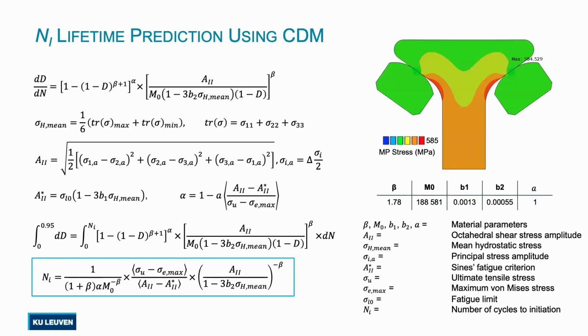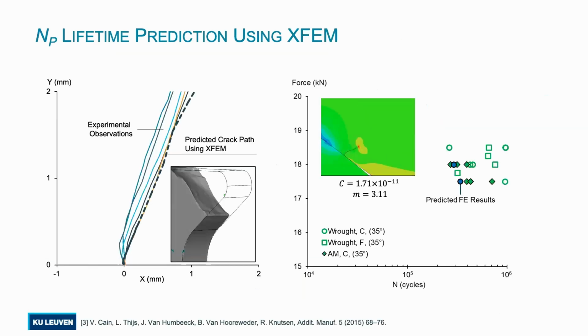We did also some simulations to confirm that. Two more slides, and we used continuum damage mechanics. The main reason for this simulation is to understand the behavior and integrate the defects inside the finite element model for crack initiation. And also we try to estimate the crack propagation path using an extended finite element model, and adding all together, you see that we can predict the results well compared to the AM material. And the next step would be integrating these defect-like features in the simulation.